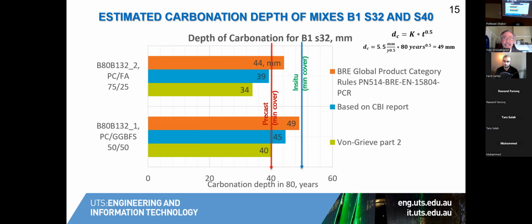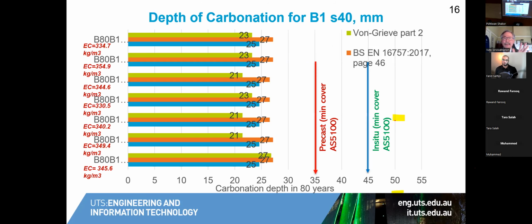Basically, under the current prescriptive requirement, we would only be able to meet the requirement for in situ concrete, which provides greater cover than precast concrete, which demands lesser cover. So very quickly, conceptually, I won't have time to go into detail, but basically to look at how perhaps we can introduce a performance-based requirement to enable producers to come up with a novel solution which satisfies the performance requirement and perhaps do away with some of the prescriptive requirement in terms of minimum cement content, because it's the minimum cement content that controls largely the embodied carbon.